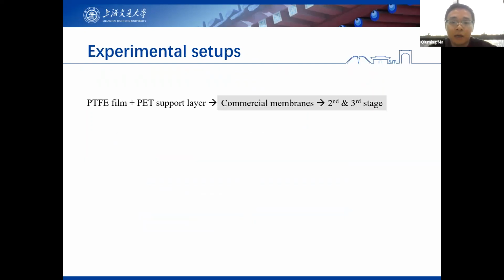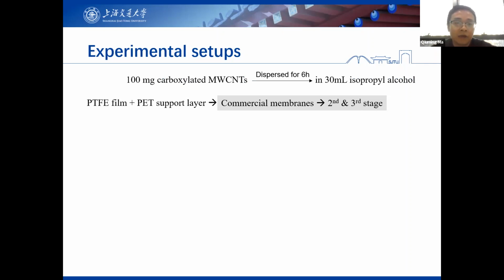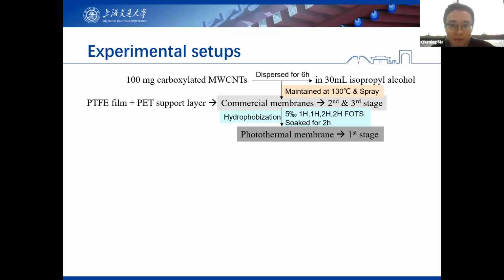For the membranes, we just use commercial membranes with the PTFE film and the PET supporting layer for the 2nd and 3rd stage. For the first stage, because in our design we used the photothermal membrane, in our lab we made it ourselves. We purchased 100 milligram of carboxylated multi-wall carbon nanotubes and dispersed it into 30 milliliter of isopropyl alcohol for 6 hours. Then we maintain the commercial membrane on a heated platform at 130 Celsius degree and spray the solution onto it. After drying, we hydrophobize the made photothermal membrane to obtain the final product.